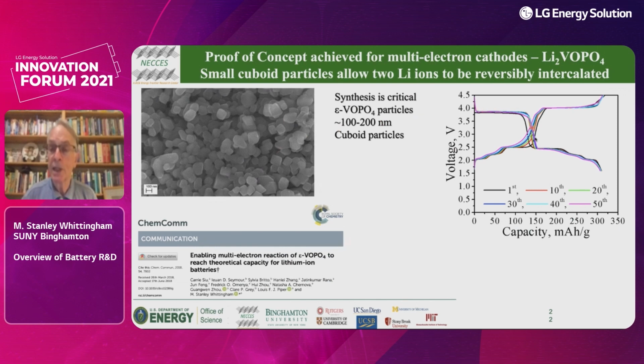And you can see here are the cycling curves, 50 of them, they all fall directly on top of each other, which shows that the material is very stable. It can sustain 2 lithiums going in and out. And if you look at this, you can see that the first cycle, the black one, and the 50th cycle, the purple one, is in fact slightly better on the 50th cycle. So clearly very stable. So we've got proof of concept that we can intercalate 2 ions into a crystalline lattice.